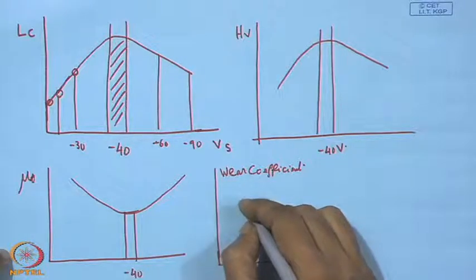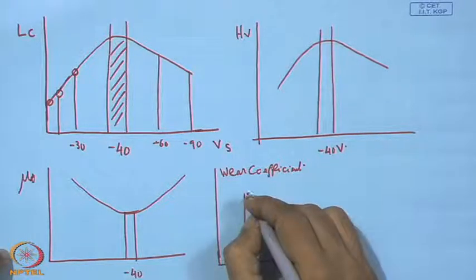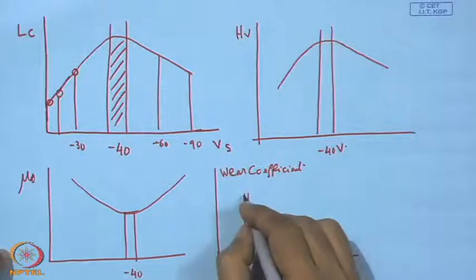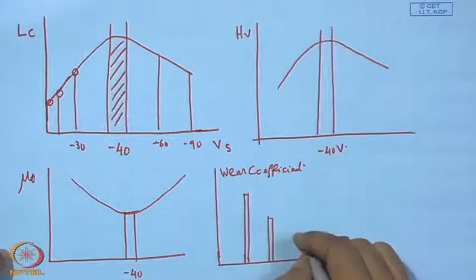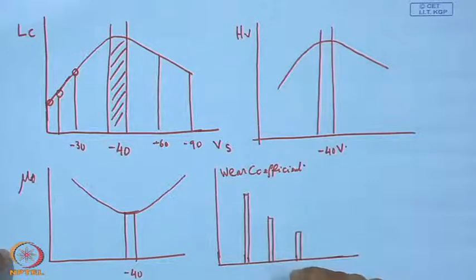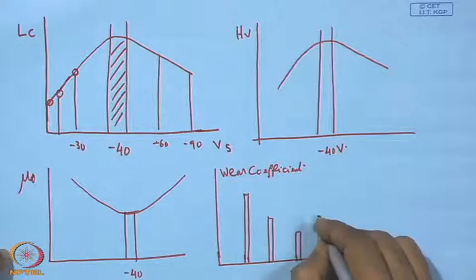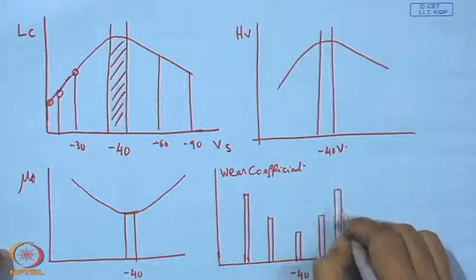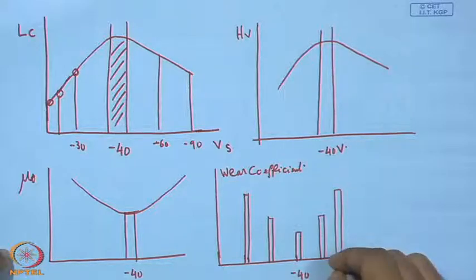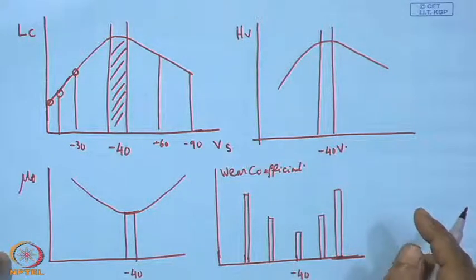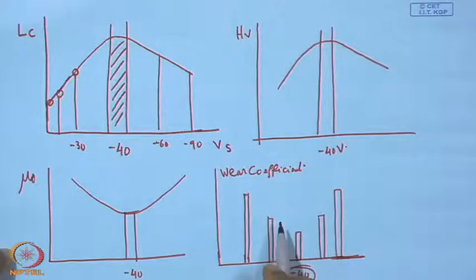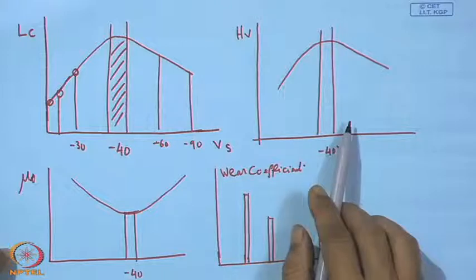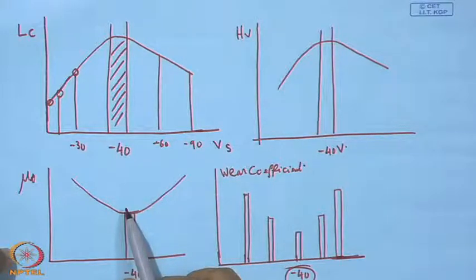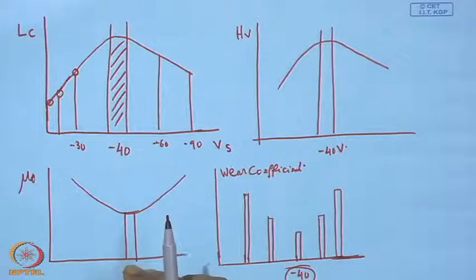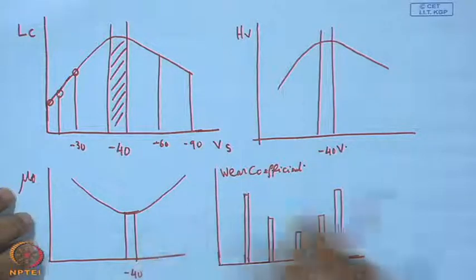So, here also we find that with this we have a high value with low bias, but somewhere around the intermediate value of minus 40 we get one of the lowest amounts of wear, with the lowest around this value, and that is because of the hardness of the coating and the low value of friction, and with this the coating can give one of the best possible performances in actual practice.